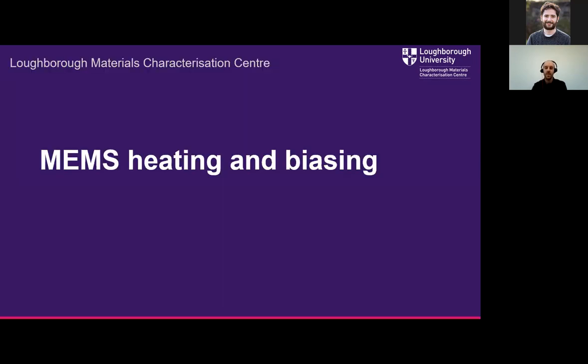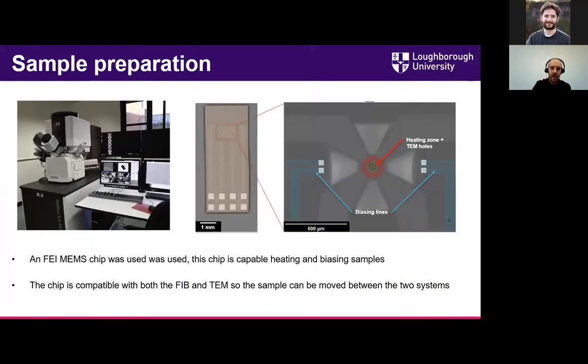Okay, so for this part of the talk, we'll move on to the MEMS in situ heating and biasing. At Loughborough, we're lucky enough to have the FEI MEMS hot stage and biasing stage. It's essentially a silicon chip with a heating membrane inside and then copper biasing lines which run towards the center. You can see right in the very center a heating zone with some little TEM holes where you'd place samples.